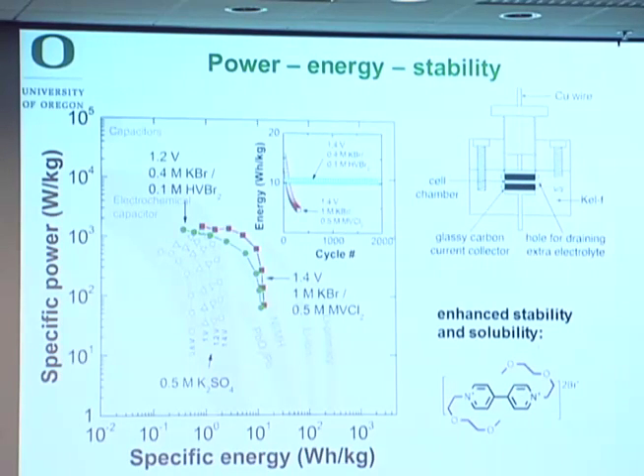So when you do this, you can see that the methyl-viologen bromide system I showed you here is really starting to access this area where we wanted to access. And we think, with further optimization and further understanding, we can drive the capacity and the power up higher. One challenge is the viologen system decays with time. It's actually known that the reduced form of the viologen can dimerize and become inactive. And the heptyl-viologen system I showed you before is extremely stable over thousands of cycles. The challenge is, of course, increasing the concentration.